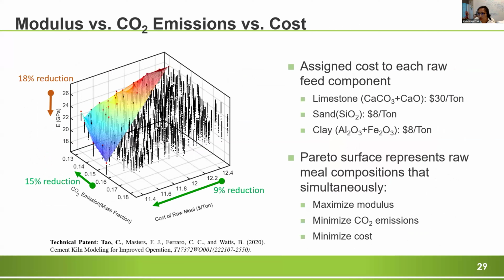And here is another case for the 3 objective function optimization. Here we want to minimize the CO2 emissions, minimize the cost of raw materials, and maximize the modulus. So this Pareto front contains the optimal solutions. So from the simulation result, the information can be used to make decisions based on the weight of the performance, economy, and sustainability. For example, if it's acceptable to sacrifice some strength, like an 18% reduction in modulus, then the sustainability and economic value will improve a lot, which is about 9% reduction in cost and 15% reduction in the CO2 emissions.